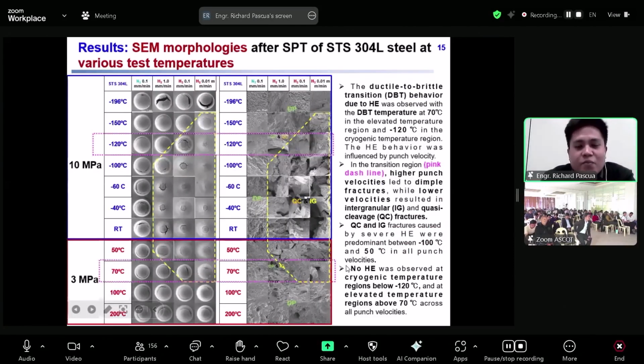If we look at the fracture morphologies obtained in different temperature conditions, under nitrogen environment, it showed a large circular crack, showing a large plastic deformation occurred in this material in different temperature conditions. And when we further observe the crack surface of this material, only dimple fracture, or ductile fracture, was observed in all temperature conditions. Under hydrogen environment, predominant dimple fracture was observed between negative 150 degrees Celsius and negative 196 degrees Celsius at cryogenic temperature and between 100 degrees Celsius and 200 degrees Celsius at elevated temperature, showing that there's no significant hydrogen effects at this temperature condition.